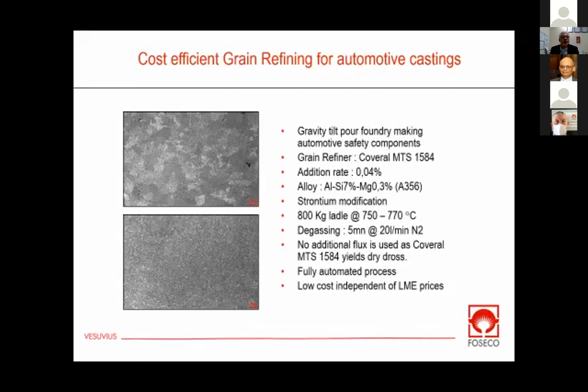If you want to make wheels, certain safety components, suspension, transmissions, and things like that—we had a lot of success in gravity automotive foundries, or suppliers who make suspension knuckles for the automotive foundry. Here's an example from one of those foundries showing grain size before and after. This sample was solidified from the melting furnace before grain refining, on top, and you can see the large grains. On the lower side, after addition of 0.04%, much lower than the normal Tibor grain refiner, you can see the structure we get.